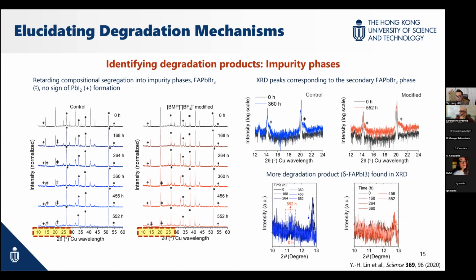Also, on the other hand, we have identified delta phase FAPbI3, which is very, very small, but it's there. But before we talk about further evidence regarding delta phase FAPbI3, it's not the perovskite phase anymore, it's actually a wide bandgap material. But one thing we observe is that we don't see the strong formation of lead iodide, because lead iodide is believed to be the degradation product of perovskite.